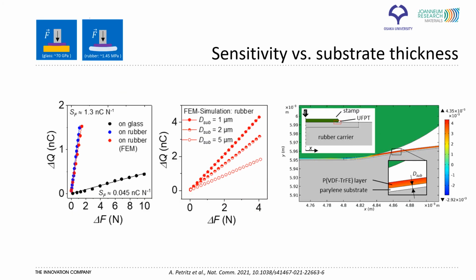When attached to an elastic material like rubber, we observe a strong increase in sensitivity upon transversal loading by a stamp as compared to the attachment on a rigid material like glass. This was also confirmed by FEM simulations, also revealing that the sensitivity increases with decreasing parylene substrate thickness. And it is also interesting to mention that the simulated strain in the piezoelectric layer is largest near the edge of the stamp.